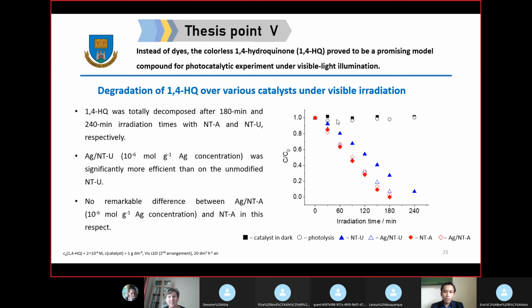The tendency was similar to the case of coumarin, in which for the N-TiO2 catalyst, the photodegradation of hydroquinone could be enhanced by silver modification, but there was no difference between the silver N-TiO2 and the N-TiO2 catalyst. Besides measuring the hydroquinone concentration, we also measured the TOC concentration during the photocatalytic experiment, and it was in line with this, as the TOC was reduced. It means that mineralization occurred during this experiment.